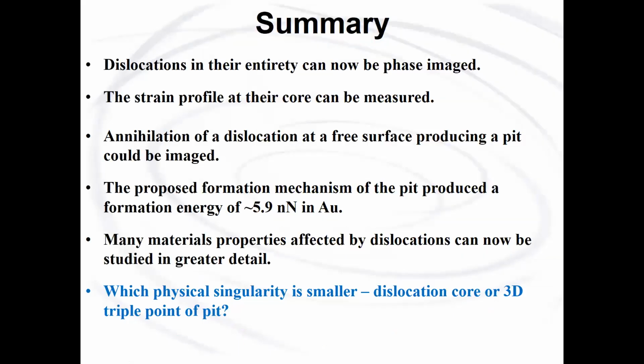So in summary, the dislocations in their entirety can now be phase imaged. The strain profile of the core can be measured. Annihilation of a dislocation at a free surface producing a pit could be imaged. The proposed formation mechanism of the pit produced a formation energy of around 5.9 nanonewtons in gold. And from this work, or method of imaging dislocations, many material properties affected by dislocations can now be studied in greater detail. And I leave you with a question: which physical singularity is smaller, the one at the dislocation core or the 3-dimensional triple point of the pit?